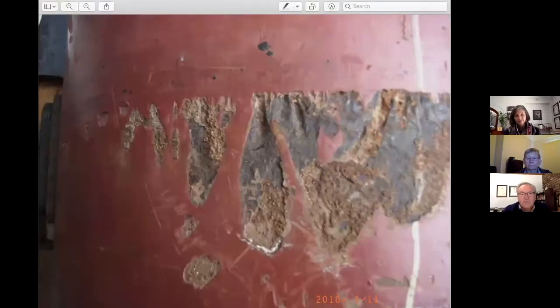And we had an interesting problem, and I'll share a picture with you, that as a result of the pipeline not being continuous, we had corrosion across the couplings. And this photograph is of an epoxy-coated section of line. And if you look across there, you can see there is a distinct line where the seal of the Viking Johnson coupling was. And this section down here, which has been corroded, was adjacent to the coupling. And the interference currents had jumped ship, so to speak, in this case jumped pipeline and gone through the ground around the coupling. And these were not railway currents.